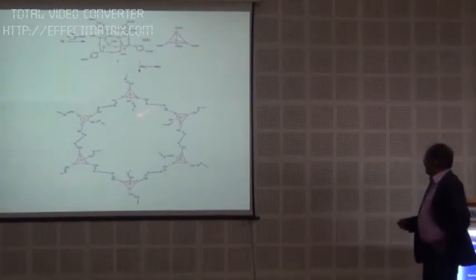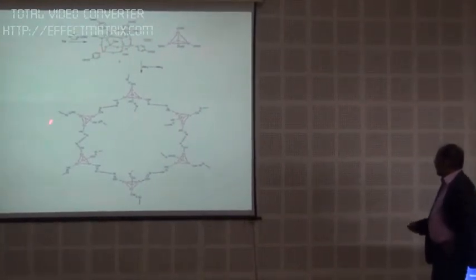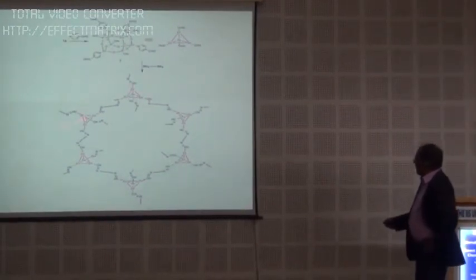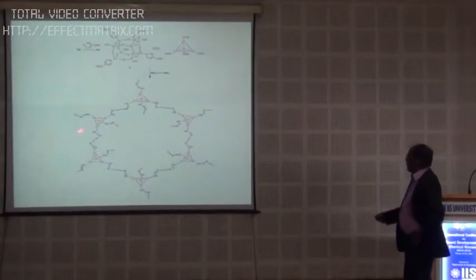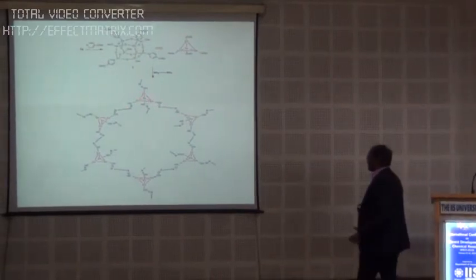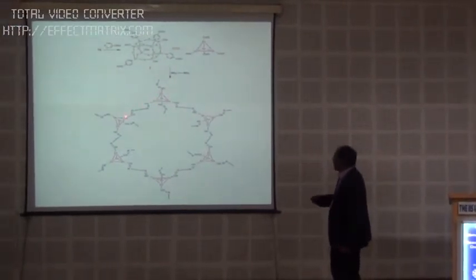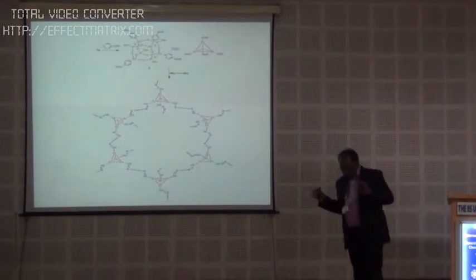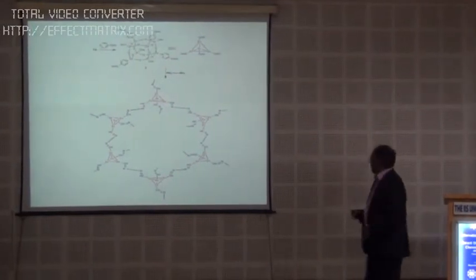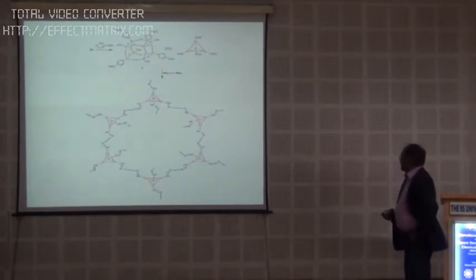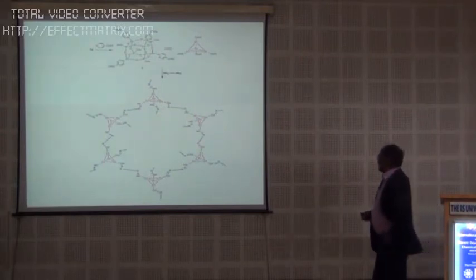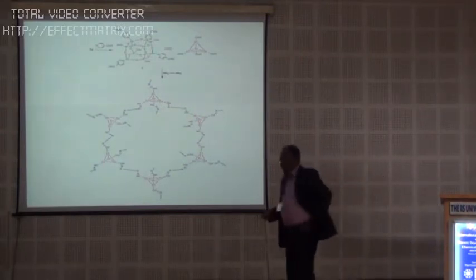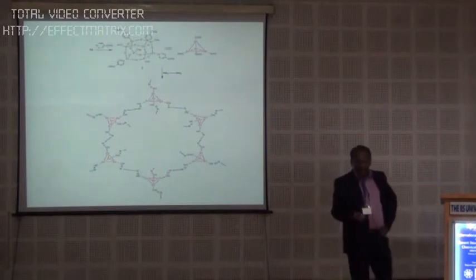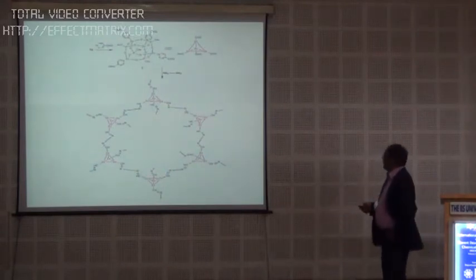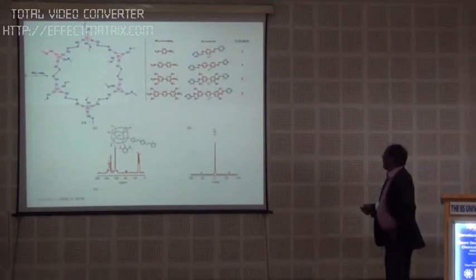And the picture is pretty much the same as what I showed you a while ago, where I had a super hexagon. Other than that, the wall of the connector was a simple bipedal molecule with no functionalities. But now I have 2 imine groups here. That means essentially this framework is loaded with a large number of imine functionalities. In organic chemistry nomenclature, it will be a Schiff base. You know what a Schiff base can do. You can actually anchor small metal particles and nanoparticles and do further chemistry with that. So this is what we did actually.